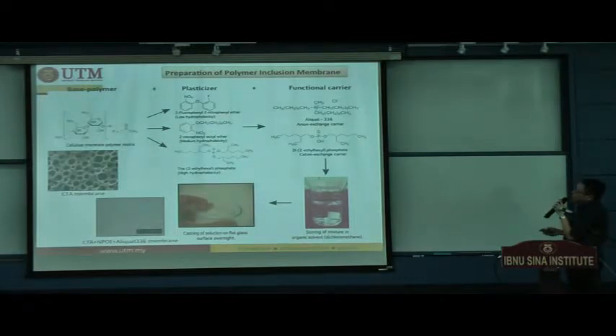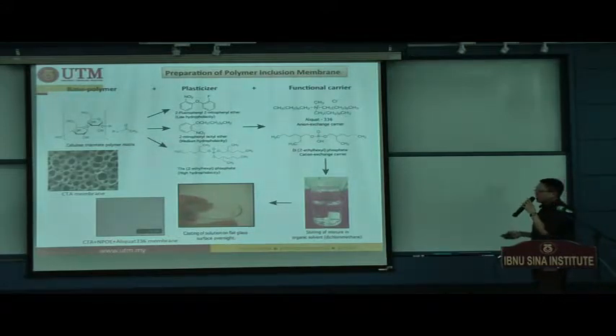These three components are mixed together according to specific proportions and put into dichloromethane solvent for dissolving, and you pour the solution onto a flat glass surface for casting overnight in a closed system. And then the next morning you just peel it off by immersing the membrane in cold deionized water. Then you will get a membrane. So it's very simple and straightforward.